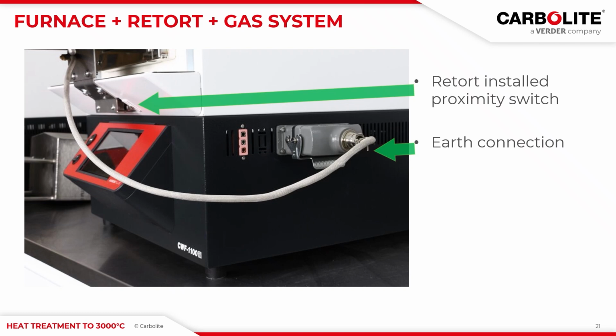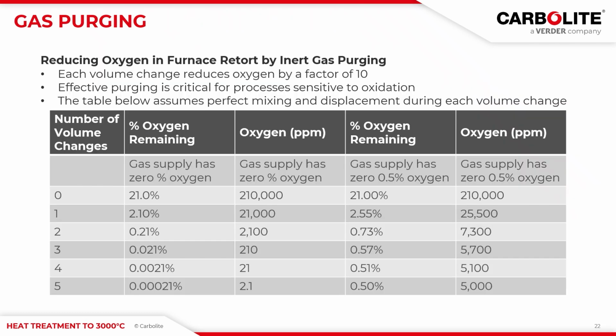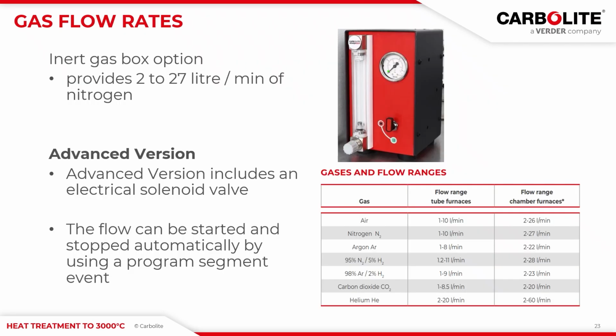The table here shows how inert gas purging reduces oxygen in a furnace retort. Each full volume change cuts the oxygen by a factor of 10, quickly lowering the levels with each purge, crucial for oxidation sensitive processes. The table displays the drop in oxygen percent and parts per million as the purge continues. With proper gas flow from back to front, the retort atmosphere becomes highly inert, protecting the components and ensuring heat treatment quality. The inert gas package, along with the retort, allows nitrogen flow rates from 2 to 27 litres per minute to suit different process needs.